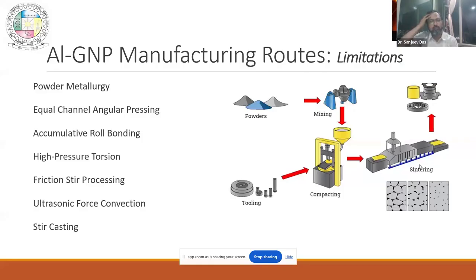You take the different powders, you mix them, and then you do compaction, and you use different types of tools to get different shapes, and then you do the sintering part. During sintering, you make the composite or the components. But the problem is when you are adding all these particles, you are not able to take out the air entrapment which is already there. So there will be a certain amount of porosity left in this kind of process.